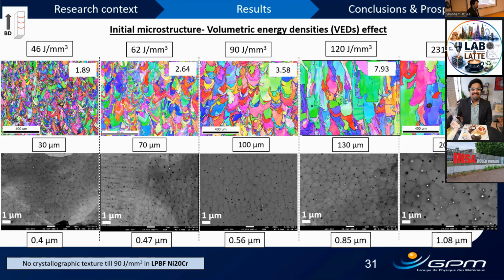Yeah, because that was my point. The mean free path, or at least the long range interaction. If we have very flat grains with complex shapes, with grain boundaries which are in fact not related to the grain size, we may have a decorrelation between the grain size and the physical barriers playing a role in the interaction, and then in the evolution of the backstress.